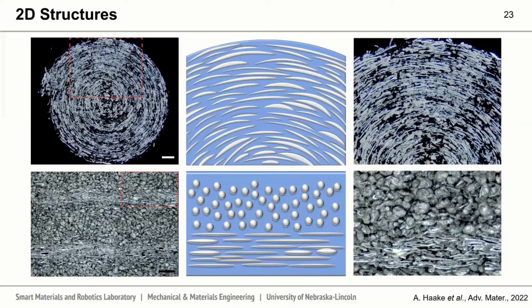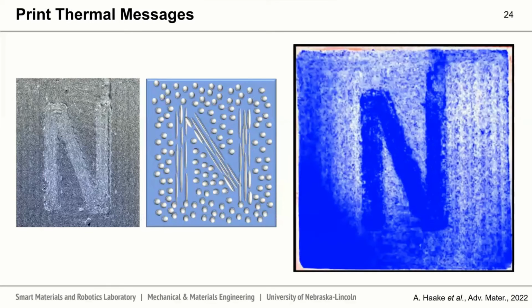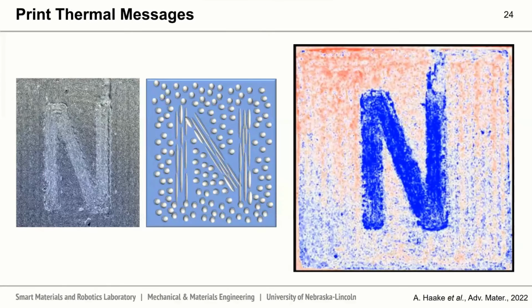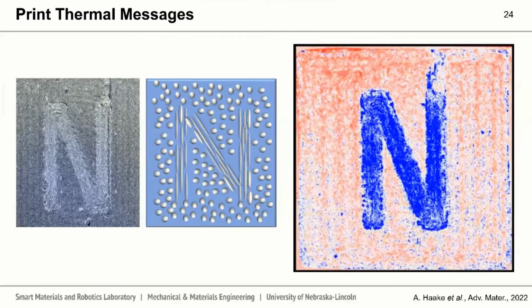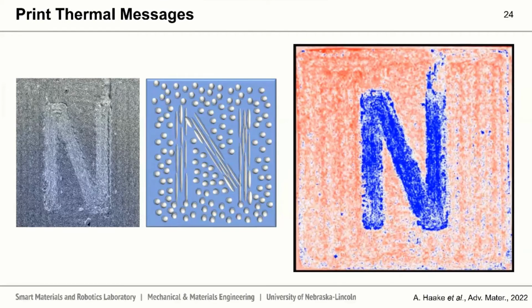We can start to print thermal messages. Here we have highly elongated droplets surrounded by spherical droplets. This allows us to decode a thermal message, or even create a heat spreader within a material.